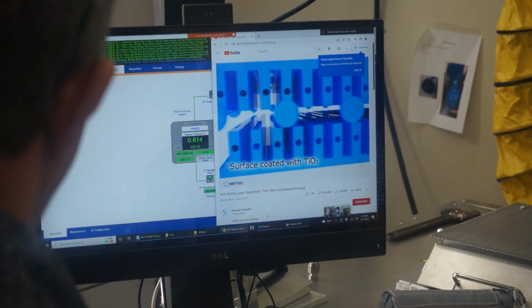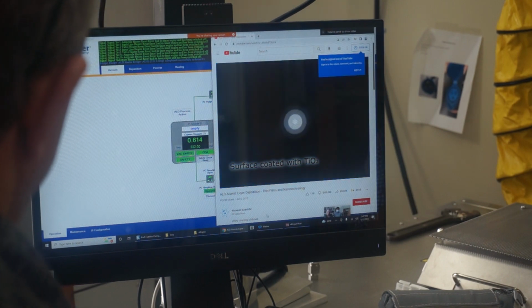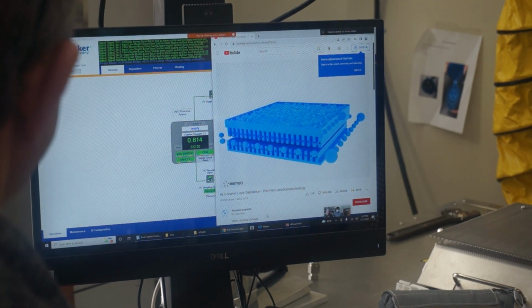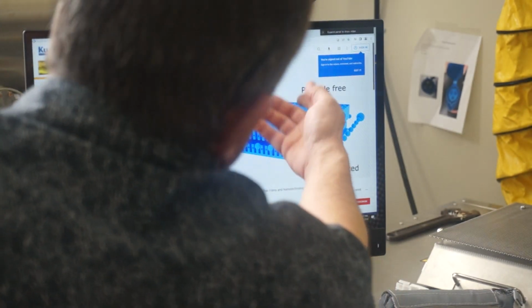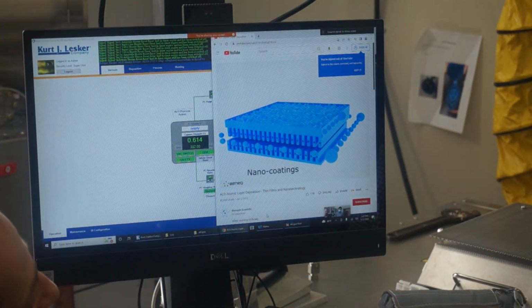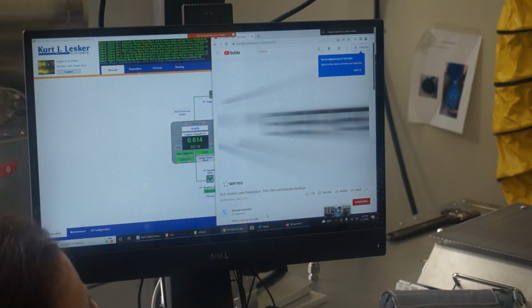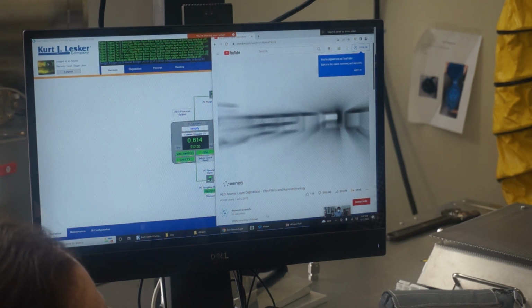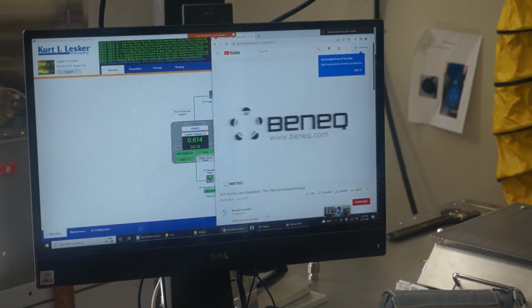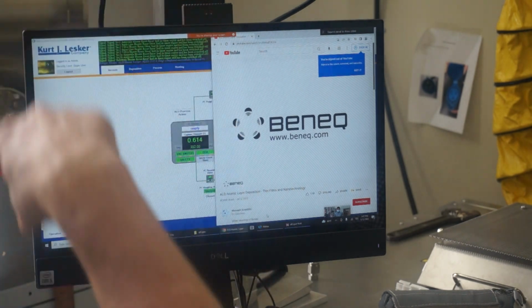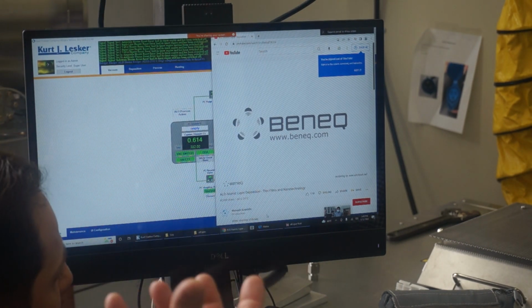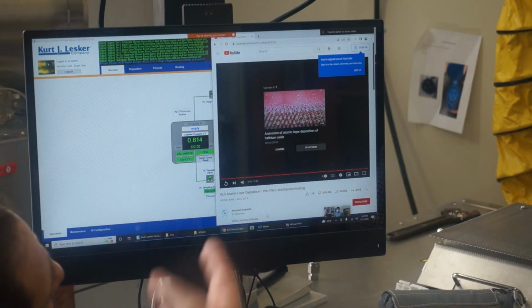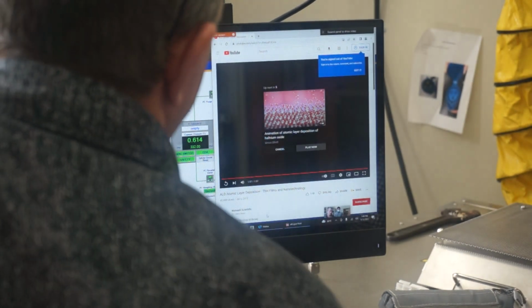It's some sort of additive manufacturing. Yeah, it is, at the atomic level. In this, you can have, again, conformal and pinhole-free coatings. So you can get in all the little nooks and crannies and super small areas. You can have very high aspect ratios and have a conformal coating all the way through any type of three-dimensional unit. It's very difficult to do there. It's good to do here.